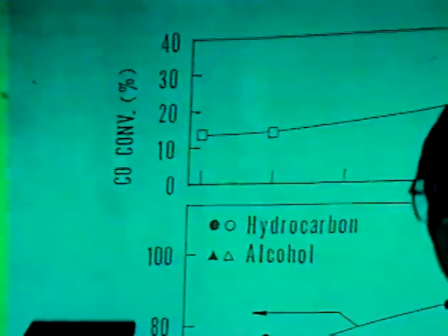The oxidized catalyst shows a steady increase as the time of exposure increased. During this period, you observe that the initially alcohol-selective catalyst turned into a hydrocarbon-selective catalyst, and the chain length increased steadily. We observed this catalyst by XPS to see the surface state.